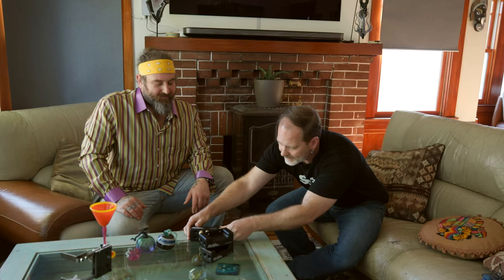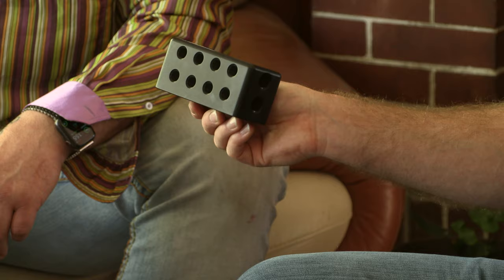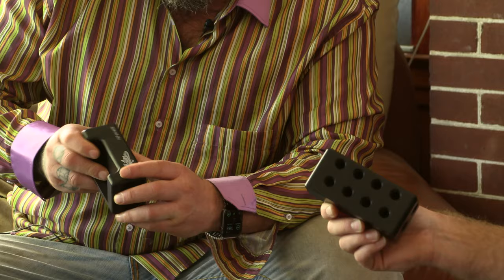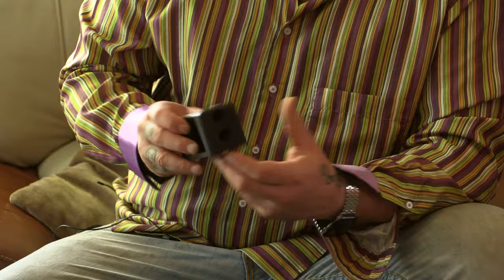Can you tell me a little bit about the process of how one of these is made? Is it made out of a couple of pieces of metal or one piece? All the profile is machined first, then we clean up the bottom and add the mounting holes. Then all the ports are drilled — each is an independent circuit all the way across. Then it gets tumble polished and anodized, laser engraved with our logo. And that's essentially it. So because it's made out of one solid piece of aluminum, there's really no place to leak but the fittings.